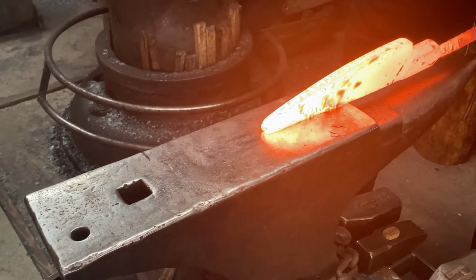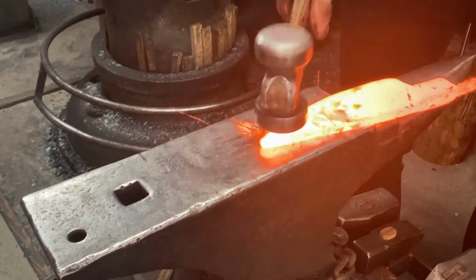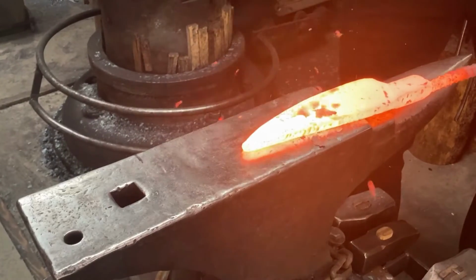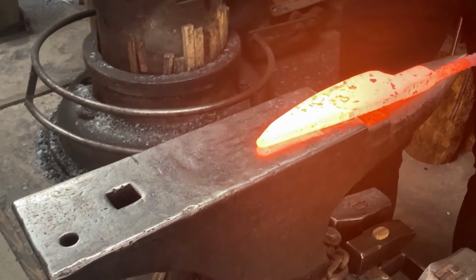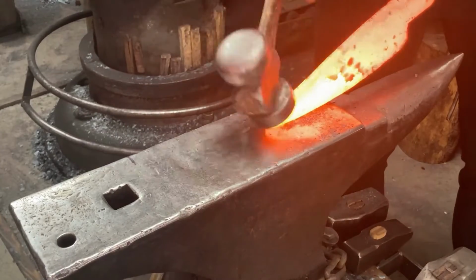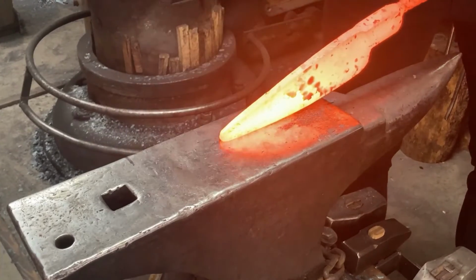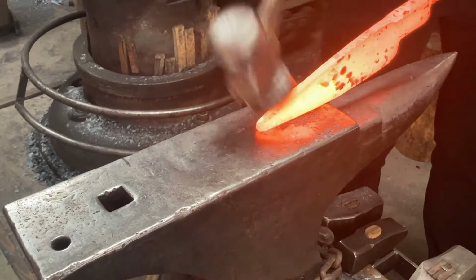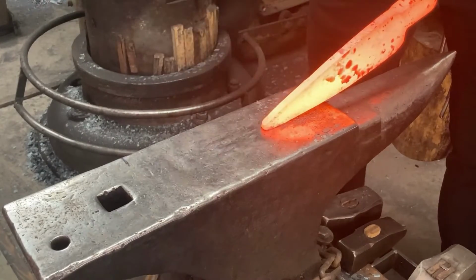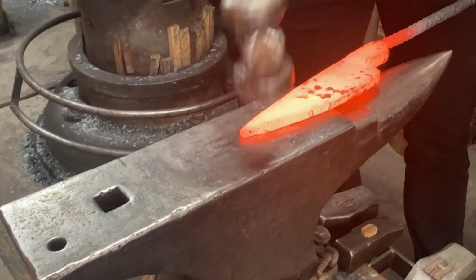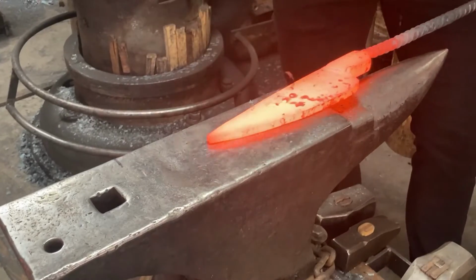Now we're going to a 4-pound combination hammer by Steve Howell of Ballard Forge in Seattle. This has a wider face and a flatter face, and this is a very good hammer once the steel gets a little thinner for just adjusting and truing everything up along the profile to everything else and taking any hammer dents out of the profile.